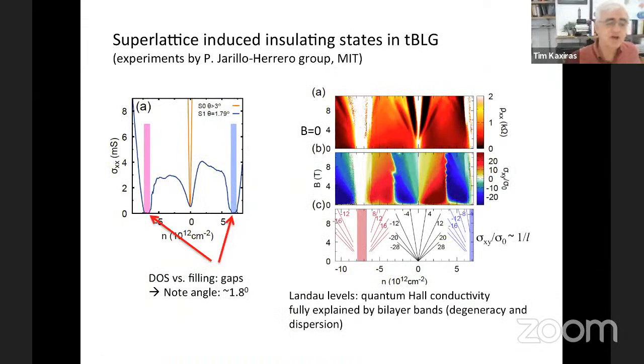And indeed, this picture was confirmed early on. So this is a set of experiments by the group of Pablo Jarillo-Herrero. And what you see here on the horizontal axis is the doping. And on the vertical axis is the diagonal conductivity. This is a measure of the density of states. So you can think of this picture as exactly measuring essentially the density of states on the vertical axis as a function of the energy, which is also related to the doping. So indeed, you see these two big humps here corresponding to the density of states of the flat bands. And these are separated from other bands by these narrow gaps.